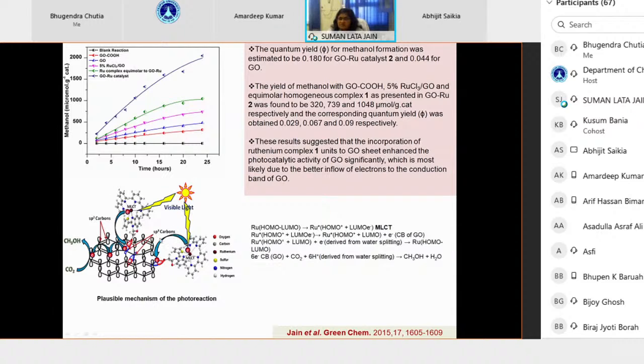The mechanism is similar. Under light irradiation, excitation of the molecular complex takes place. Electrons go to the conduction band, and one of the important parameters is that the unsaturated support provides higher electron mobility. Due to this improved mobility of the electrons, the recombination of electrons and holes is diminished, and the carbon dioxide molecule has higher electron availability for its conversion.